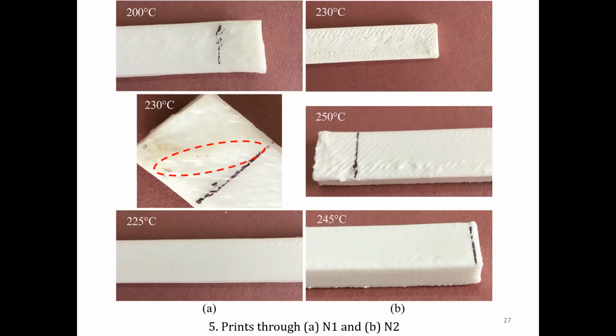Figure 5B typically shows representative print images of H60, as this combination has the maximum GMB content. That is, it has the lowest content of matrix across the chosen compositions. We did not go beyond 60 for the obvious reason that, based on our pilot studies, there is an agglomeration, filaments get rough, and when the filament gets rough, it is brittle. And again, the diametrical variation goes beyond plus minus 50 microns, wherein the printer clogs and the filament jams, and that's how we limited it to 60% volume fraction in high density polyethylene.